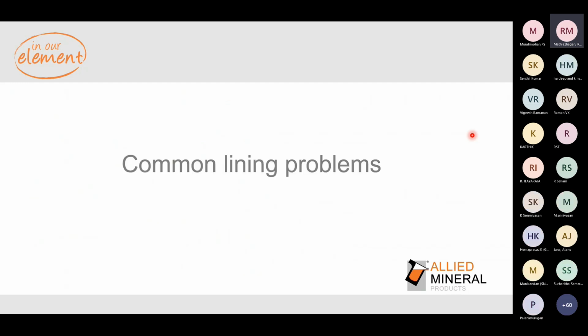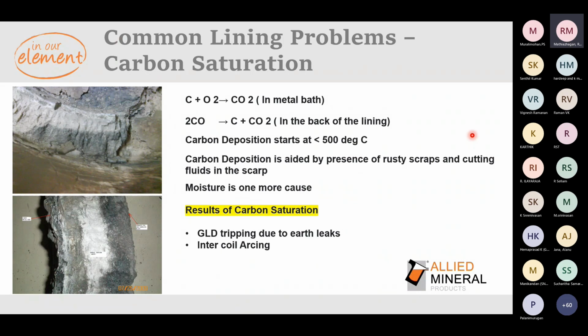So coming to common lining problems. One common lining problem is carbon saturation. If you see this picture, this is the hot face, and on the cold face side you can see a black spot. In the picture below it's the same thing: the hot face on this side, a middle portion which is white, and on the cold face a black portion. It is all because of carbon deposition. Carbon deposition starts because the temperature is always lower as it goes near the coil. Below 500 degrees Celsius the carbon deposition starts, and it is aided by the presence of rusty scrap and oil in the borings or oil in the scrap. Moisture is also one more cause for carbon saturation.